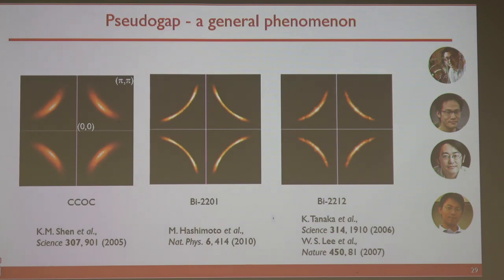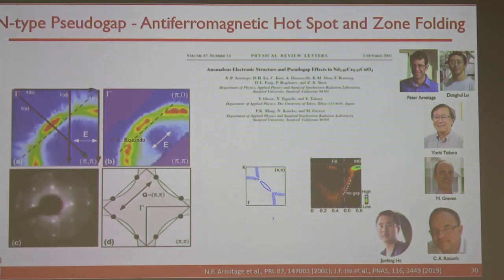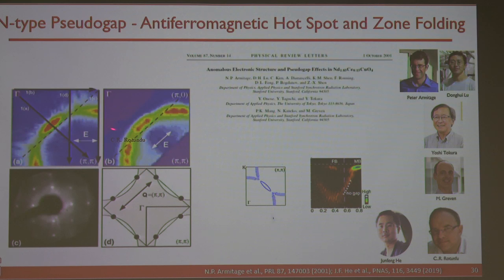So it is difficult. But on the other hand, the electron-doped system turned out to be a very good way to gain some insight. And you have this so-called hotspot phenomenon. The red is the underlying Fermi surface. You notice that the spectral intensity is suppressed where this underlying Fermi surface and the antiferromagnetic zone boundary cross. This we call the hotspot. Okay? And of course, the magnetic scattering in this case could give you something reminiscent of the pseudogap. So we will say at least antiferromagnetism is a component of the pseudogap phenomenon.